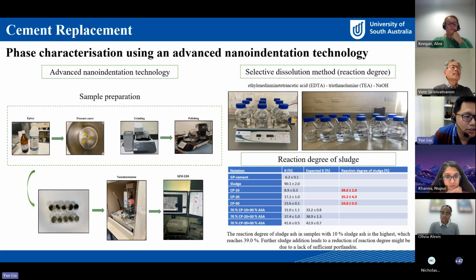surface for the nano-indentation test. For the selective dissolution method, we found that the reaction degree of sludge in samples with 10% sludge is the highest, which reaches around 39%. But further sludge addition leads to a reduction of the reaction degree due to a lack of calcium hydroxide, because when we increase the sludge content, we definitely reduce the cement content, and also the produced calcium hydroxide.